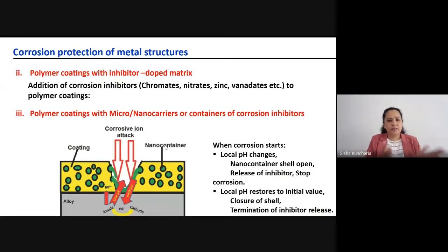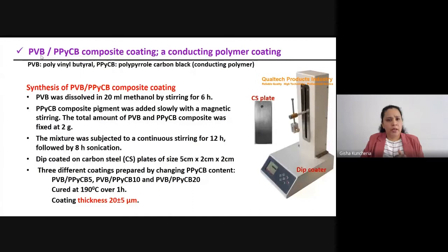So based upon all these literature ideas, we prepared some coatings. By adding a conducting polymer, here the polymer matrix is polyvinyl butyral and the conducting polymer is polypyrrole. So we synthesized 3 formulations by changing the conducting polymer composition, and all 3 compositions were dip coated. This is the dip coater used, onto carbon steel 5 by 2 by 2 centimeters in size. The dip coater is a very useful technique. You can control the thickness and get a uniform coating.